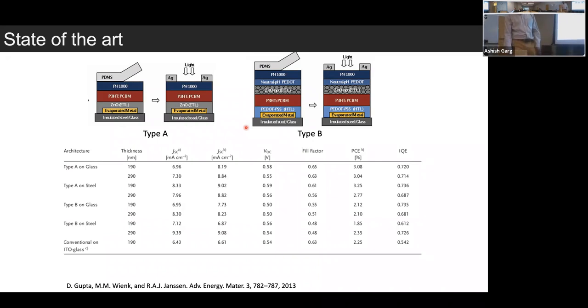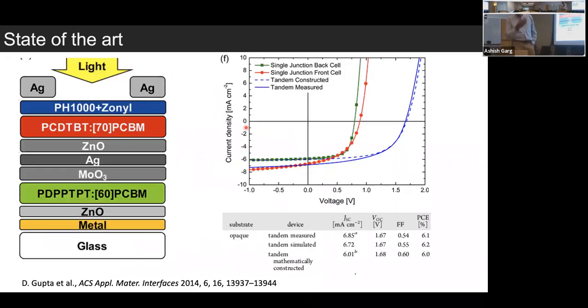It really depends, but the problem with these was that they used silver electrodes, or they made grids of two different compounds, which is a quite cumbersome way of making an electrode with lower transparency. You can also make a tandem device, but that is far more difficult. I mean, a single junction device itself is very difficult, but people have worked on tandem cells, reaching efficiencies of about 6%. And in our work, we used a single layer device to achieve an efficiency of the order of 6%.